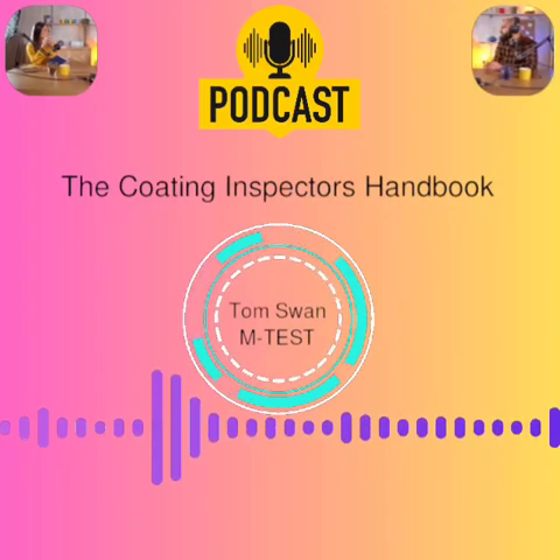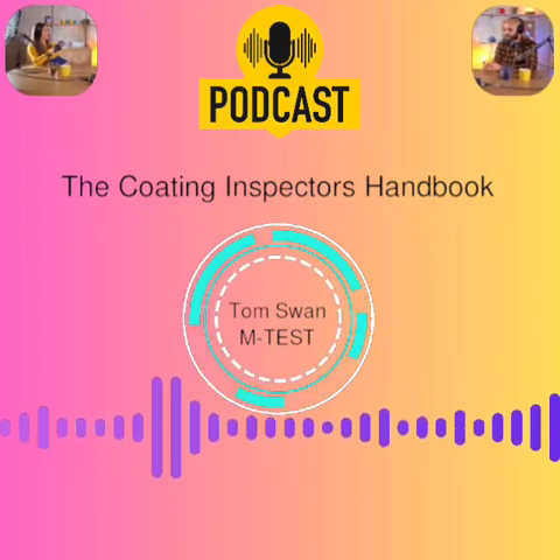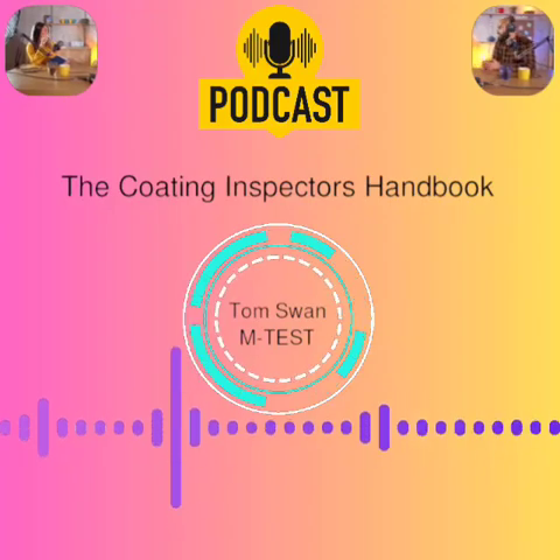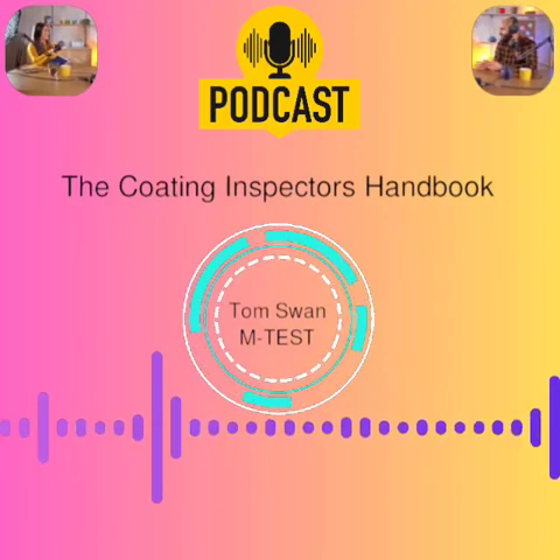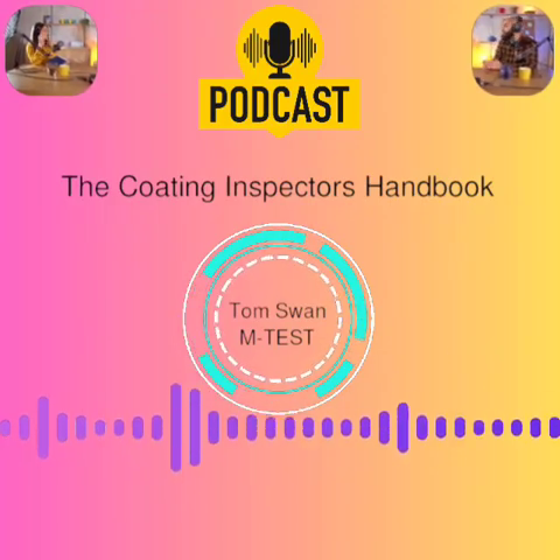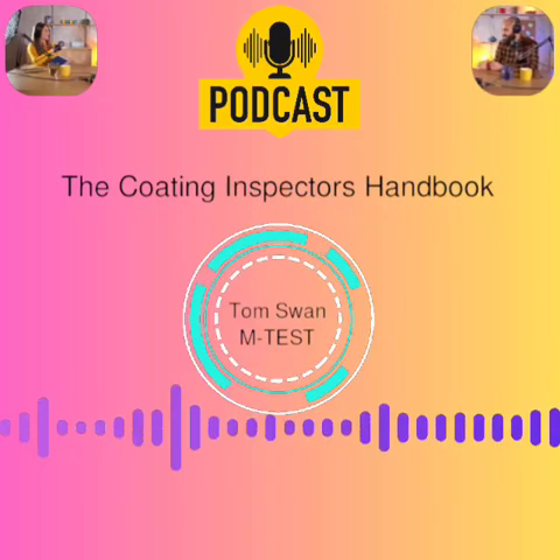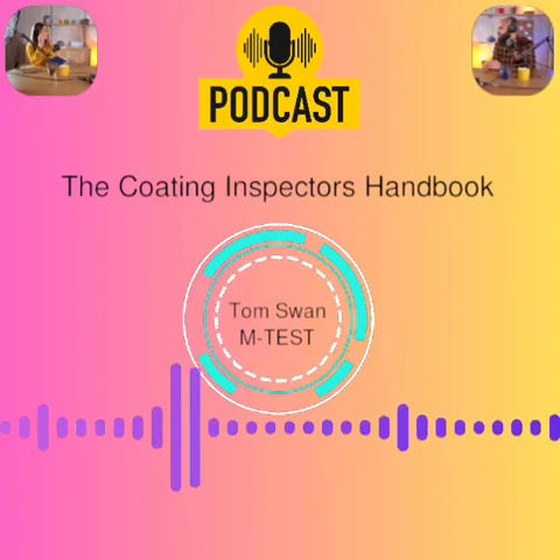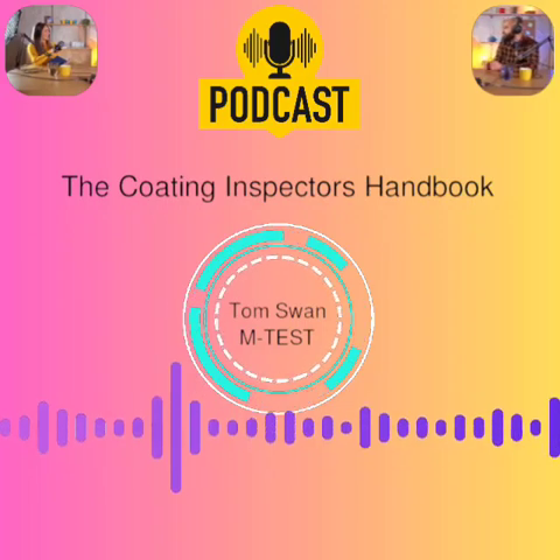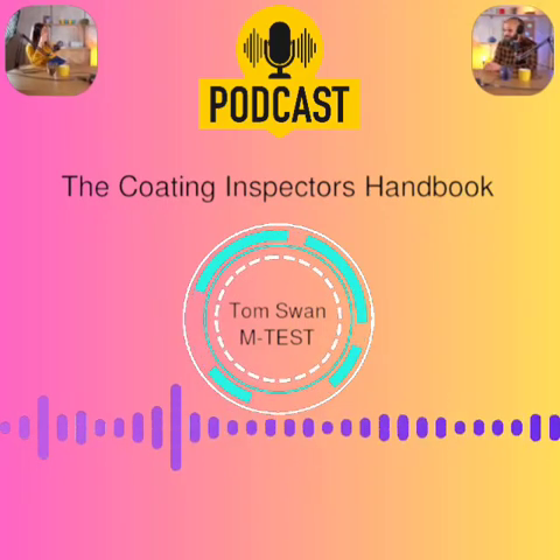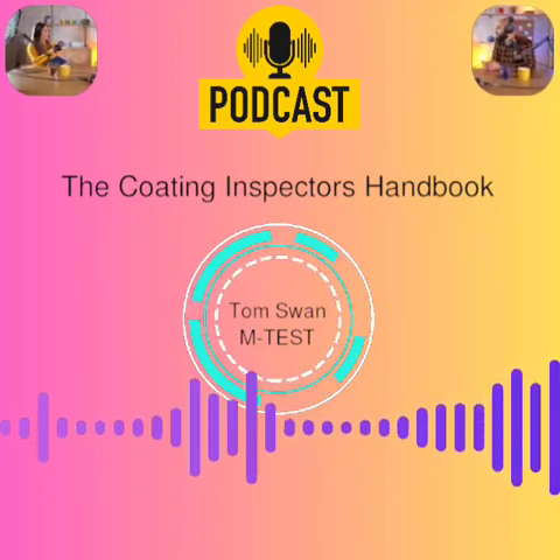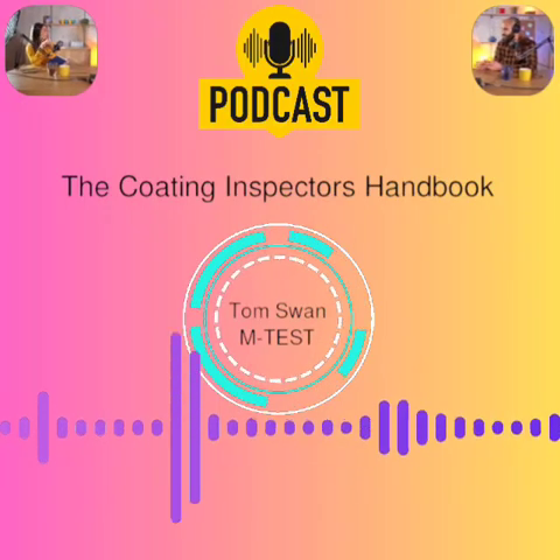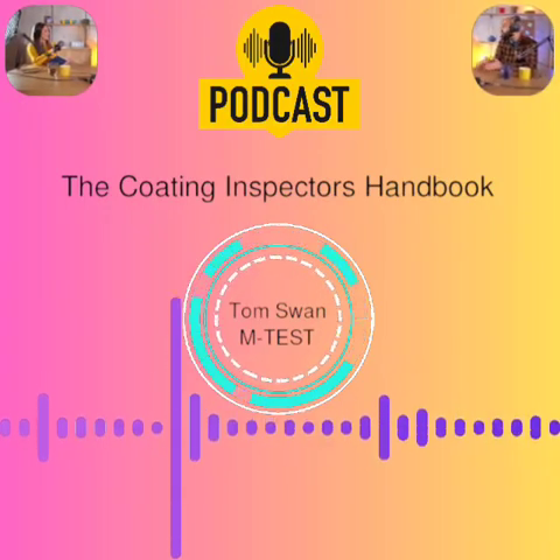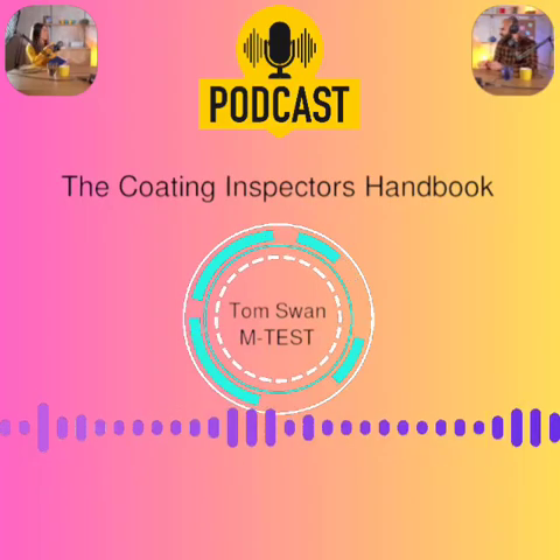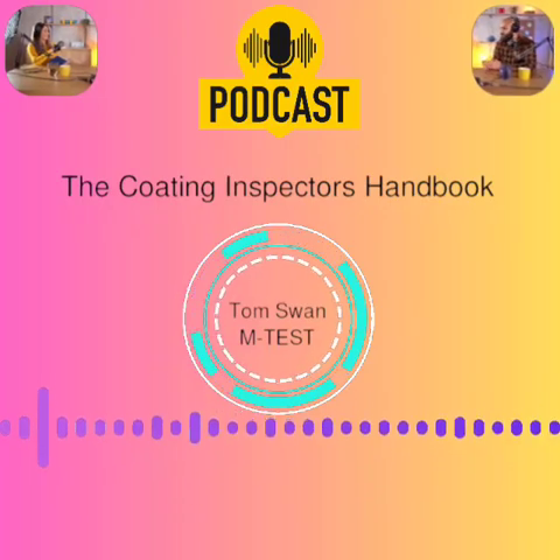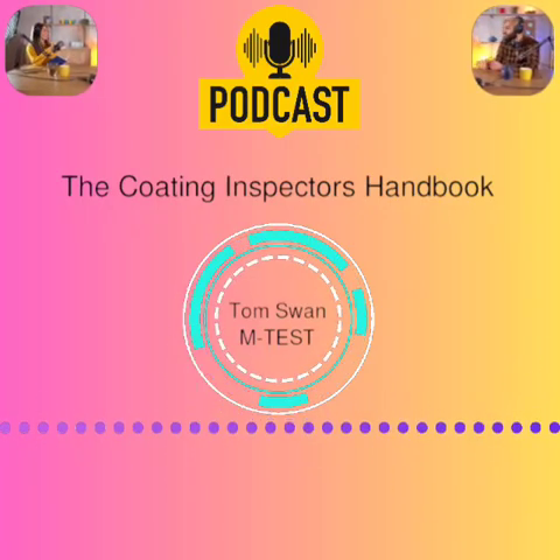And how does that profile affect the amount of paint needed? Big impact on cost and coverage. A deeper profile means more surface area, more valleys to fill. So you need more paint. Significantly more paint just to fill that texture before you start building measurable thickness on the peaks. Rule of thumb: for every 10 mils of profile, you might need extra paint equal to about a 5 mil DFT coat. Maybe 0.5 times the profile depth. Well, that's for smoother profiles. Yeah, maybe 0.25 times for shot blast. This extra paint fills the valleys. It doesn't add to your DFT reading until you're above the peaks.